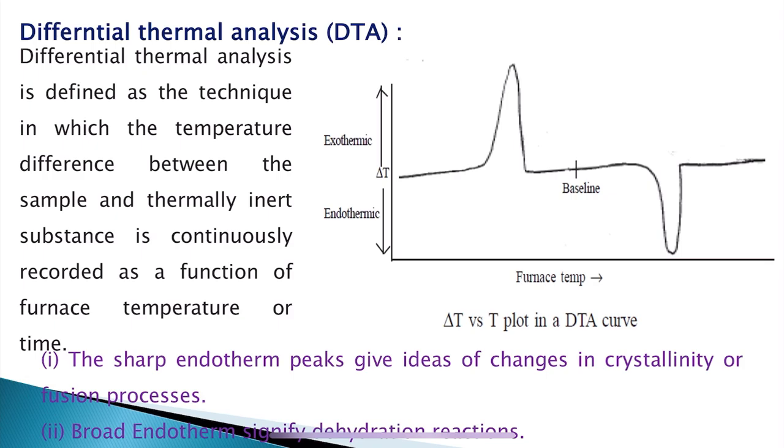There we saw at what temperature the decomposition of silver nitrate takes place, and till what temperature, that is 608 degrees centigrade. Till 608 degrees centigrade, the loss in mass continues, and the mass of the sample remains constant beyond this temperature.